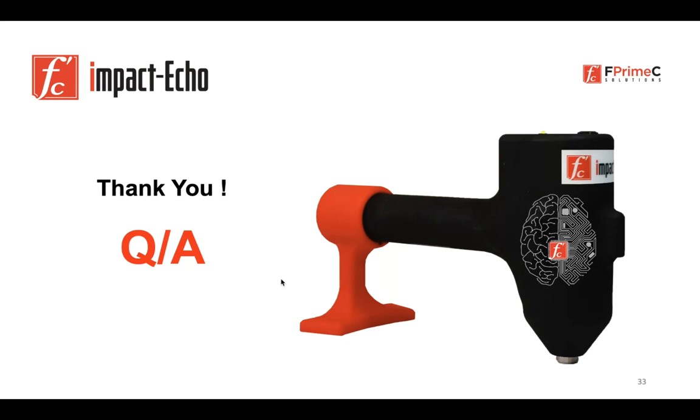If they want to use the Impact Echo for those materials, I strongly recommend they take a core from the concrete and measure the velocity with other technology like UPV and have a benchmark. And when they have a good benchmark of the P wave velocity for those materials, they can do the test with the Impact Echo.